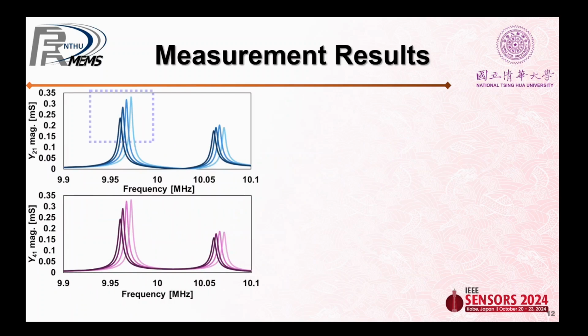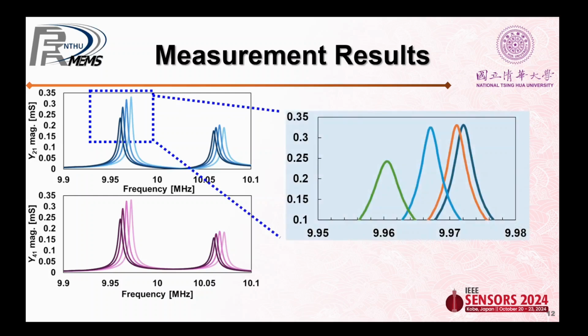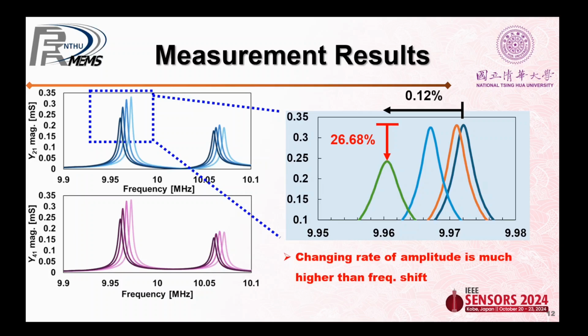And let's zoom in on the first mode of the first resonator as a demonstration. The rate of change in amplitude is around 26%, while the rate of change in frequency is only 0.12%. The significantly higher rate of change in amplitude compared to frequency highlights the benefits of mode localization.